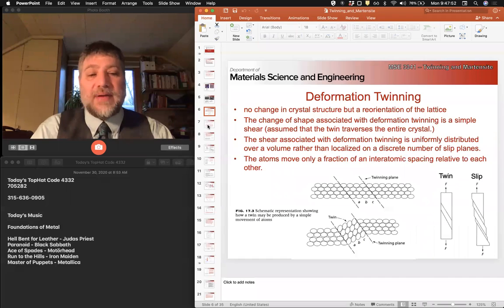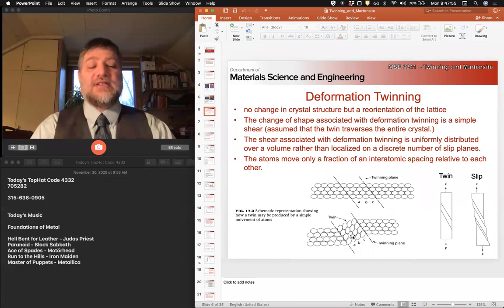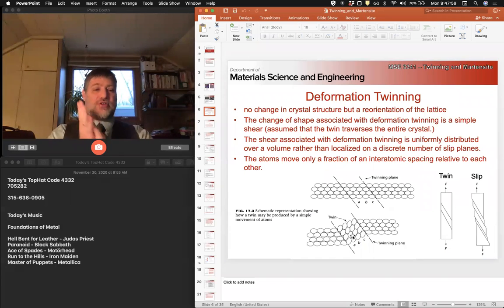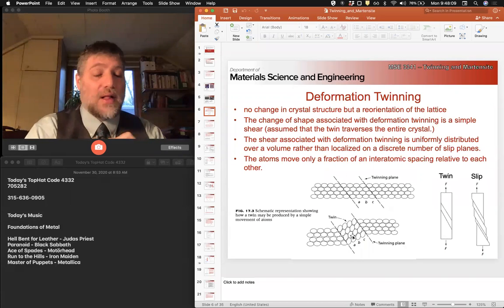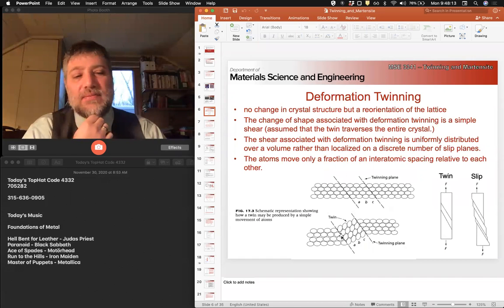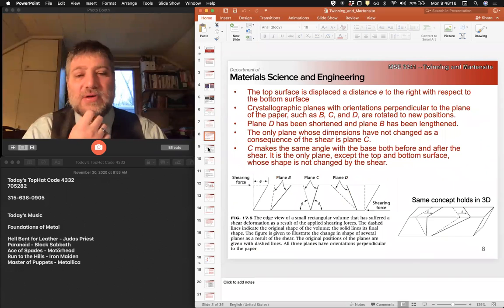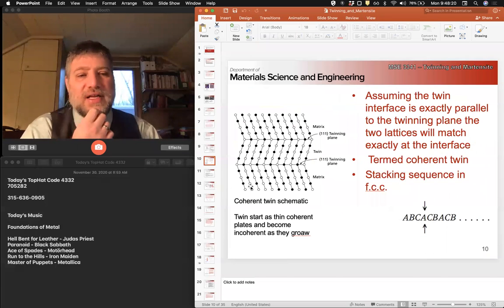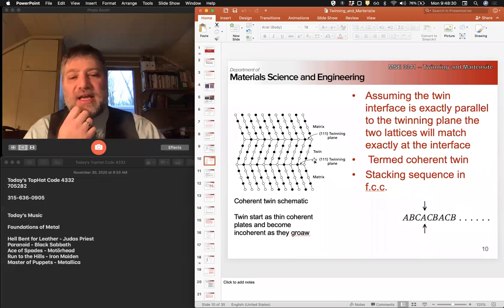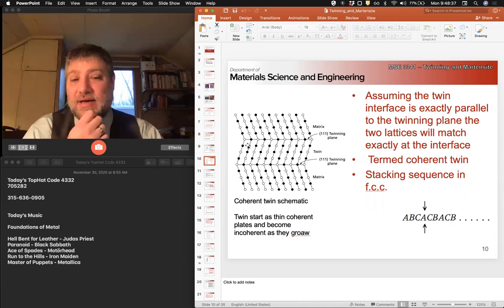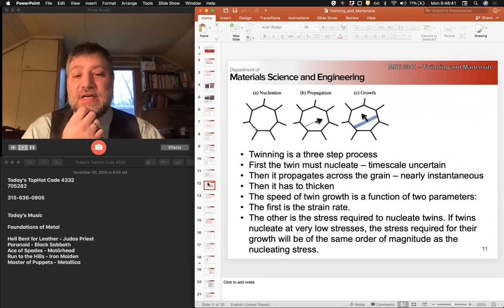And I talked a little bit about deformation twinning to basically set up how you can have a transformation of the lattice that involves a large rotation of the lattice, and that generally there's shear involved, right? Twinning goes from the same crystal structure to the same crystal structure. So in case of FCC, it goes from FCC to FCC. And we have a 60-degree rotation about 111, which gives us essentially an error in our stacking sequence. Instead of ABC, ABC, we now go ABC, ACB, ACB in the twinned region.